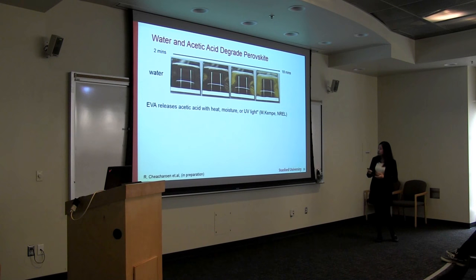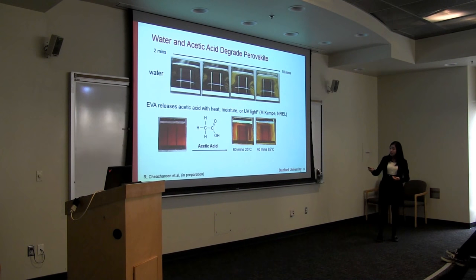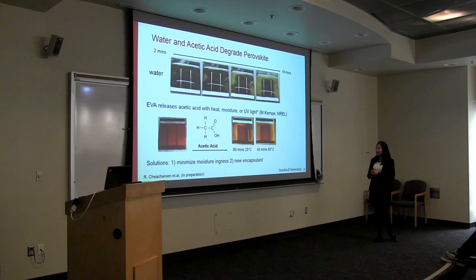The third thing is that we know, according to M. Kempe, that the EVA could release acetic acid when we heat it up, or when moisture gets to it, or when we shine UV light on it. It was unclear whether this acetic acid would degrade the perovskite, but my hypothesis is it will. So I put acetic acid on top of my perovskite solar cell and I saw a discoloration as well. In this case, this is at room temperature for 80 minutes, and just as we heat it up, it reacts faster. So with these two problems, we should try to fix them by minimizing moisture ingress and, we should select a new, non-reactive encapsulant so that we don't have this problem.